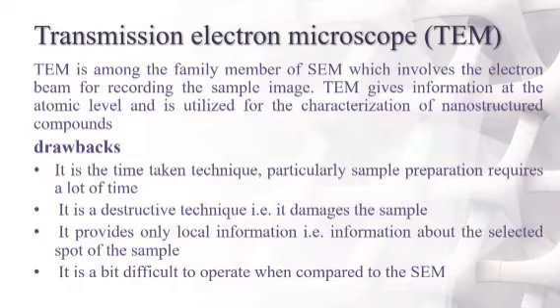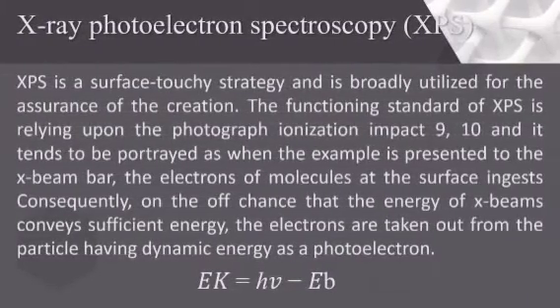TEM has certain drawbacks. Sample preparation is time-consuming. It is a destructive technique that can damage the sample. It provides only local information about the selected spot of the sample, and it is more difficult to operate compared to SEM.